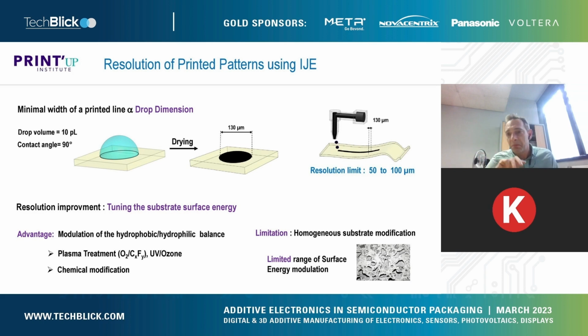You can adjust the substrate surface energy to improve the contact angle, for example increase the contact angle, and thereby decrease the line width you are able to print. This is very interesting, and there are a lot of techniques to modify the substrate surface energy. You can use plasma treatment, UV ozone, also chemical modification.